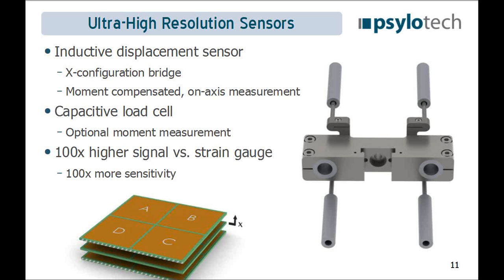So that's the core technology difference of this compared to, let's say, a macro scale Instron: we have this extra technology that allows for high resolution, which of course has other benefits. If you have a lab where different people are running different kinds of tests with different load ranges, you don't have to keep swapping out the load cell, because you have so much sensitivity in this load cell. Similar with the displacement sensor, you can have the same setup handling nanometers or tens of nanometers of motion, or pulling on an elastomer 30 millimeters. So that's the flexibility of this load frame.